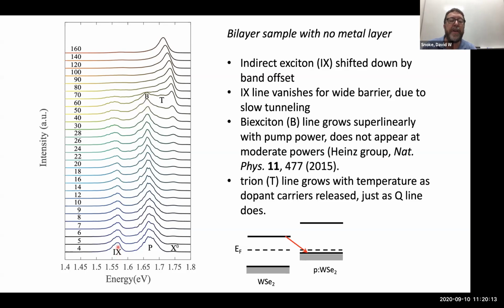So you only see the indirect exciton when you have a fairly thin barrier between those two layers. And in this particular data set, the pumping power was fairly high. So we actually see the biexciton appearing exactly where Tony Heinz's group saw it. This is an intra-layer biexciton, not an indirect biexciton. It's within one monolayer. It just happens that in this set of data, we were pumping with enough power that we could see significant biexciton emission.